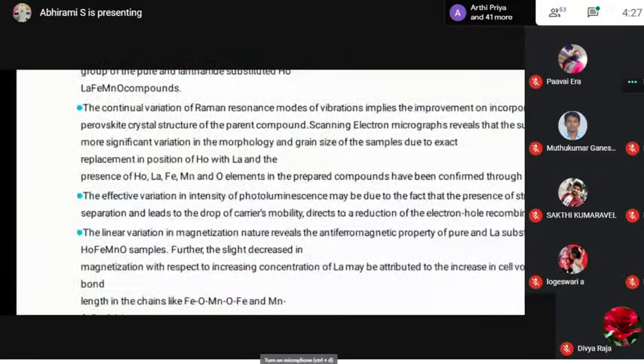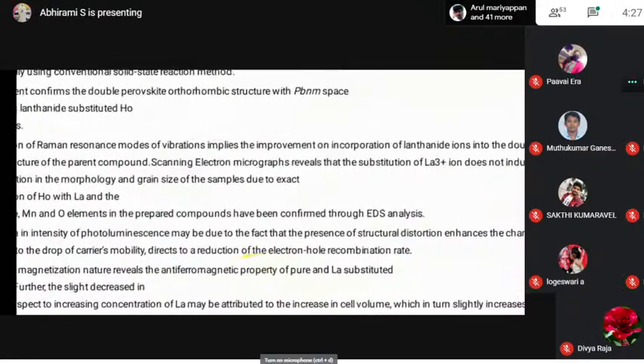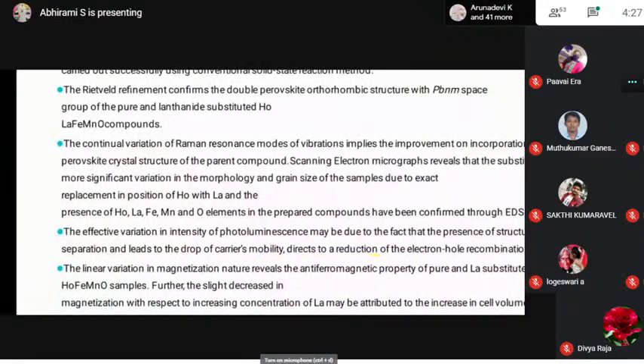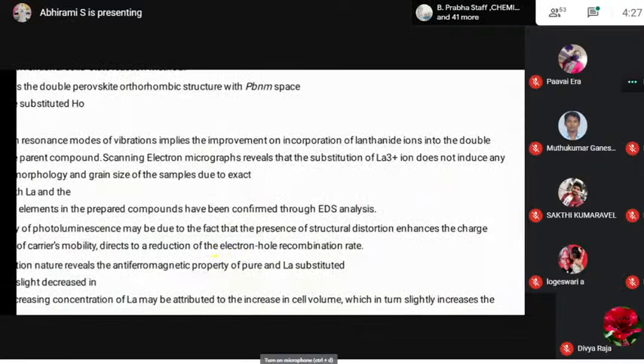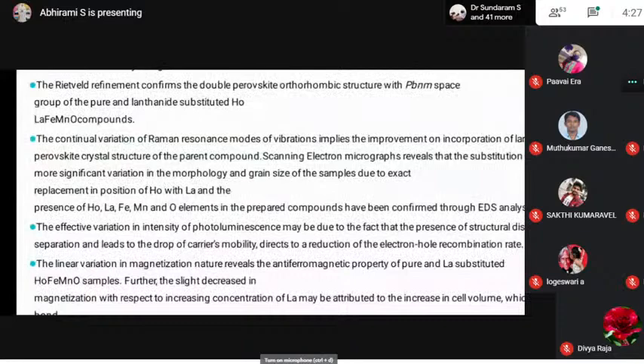Conclusions. The phase stabilization of the double perovskite Ho2FeMnO6 compounds has been carried out under the conventional solid-state reaction technique. The Rietveld refinement confirmed the double perovskite orthorhombic structure with Pbnm space group for the pure and the La substituted compounds. The continual variation of the Raman resonance modes of the vibrations implies the incorporation of La3+ ions into the double perovskite crystal structure of the parent compounds, and the SEM images reveal that the substitution of La3+ ion does not change the morphological structure of the prepared compounds.